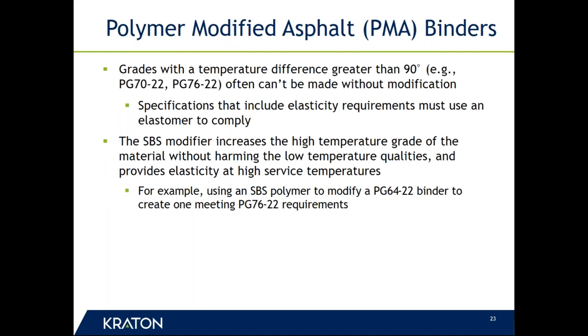Okay. All right. Well, I think most folks on the line have heard of polymer-modified binders. And as I pointed out on the TxDOT slide, there are elasticity requirements that are applied to binders where people want to specify those. Typically, when you get above 90 degrees in that grade difference, that is, the absolute difference, 70 minus 22, for example, that difference would be 92 degrees. Whenever you have grades with more than a 90 degree difference, it's very difficult to meet that criterion without modifying the binders. Not impossible, but difficult.